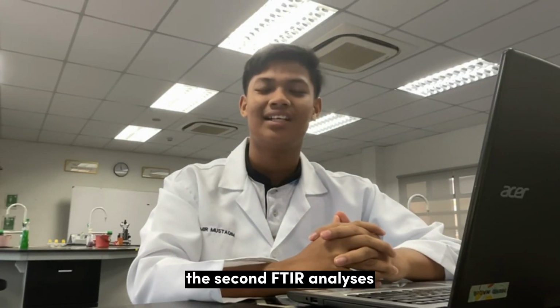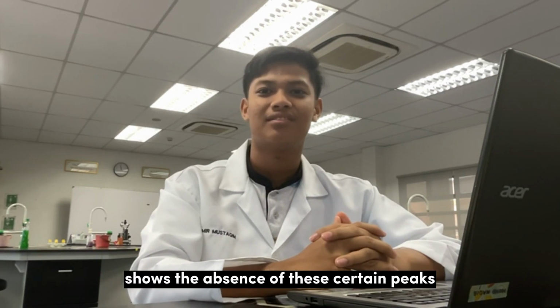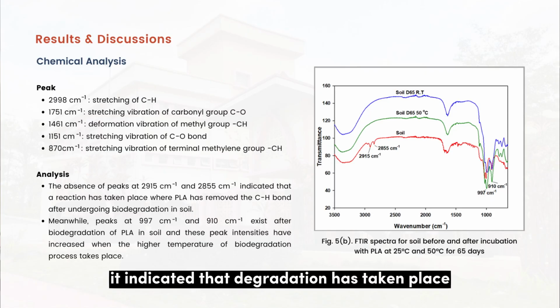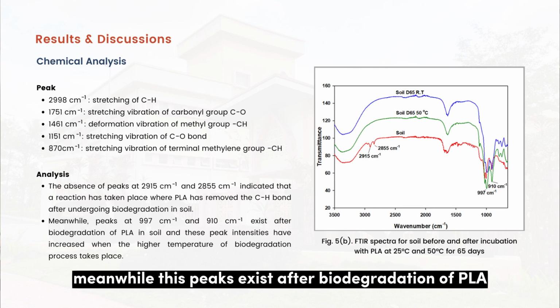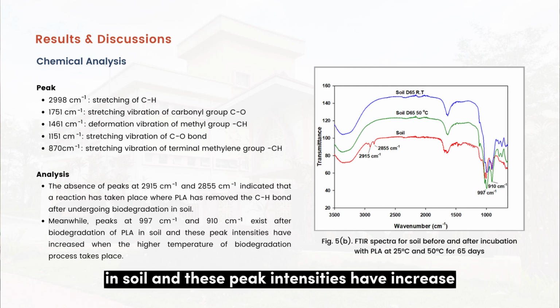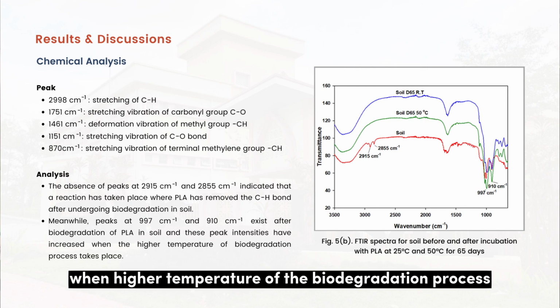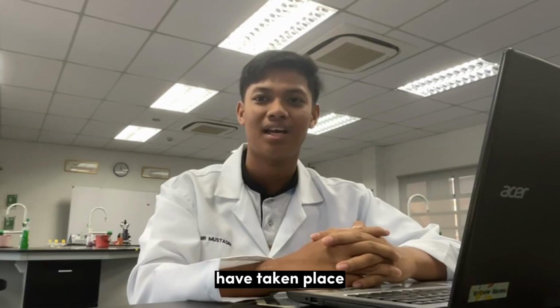The second FTIR analysis shows the absence of these certain peaks. It indicated that a reaction has taken place where PLA has lost the CH bond after undergoing biodegradation in soil. Meanwhile, these peaks exist after biodegradation of PLA in soil, and these peak intensities have increased when a higher temperature of the biodegradation process has taken place.